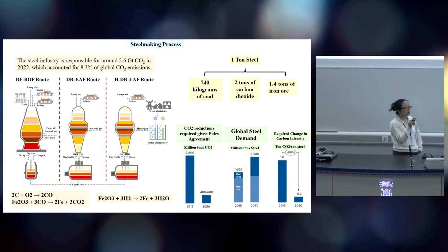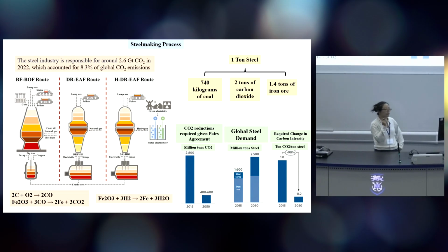There are 2 conventional steel making processes. One is, as we know, the blast furnace route, and the second is the direct reduction route. And both routes require iron ore, which is reduced to pig iron, emitting carbon dioxide by adding coal. And nearly 17% of the carbon emission in steel making is generated in the pig iron process. And as reported, the steel industry is responsible for around 2.6 billion metric tons of carbon emission, which accounts for 8% of global carbon emissions.